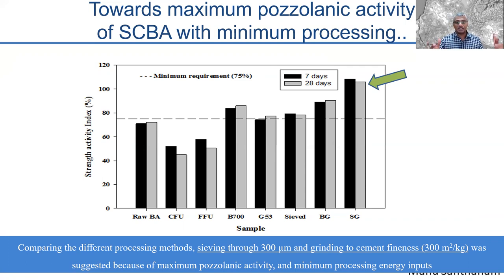So you take bagasse ash as collected, as available from your dump sites, and you dry it, because when they dump this ash, they always mix it with water to ensure that the dry powder does not fly away. That will cause health hazards, right? So you bring it, dry it, and then sieve it through a 300 micron sieve that gets rid of your fibrous carbon. What remains is your nice powdered silica.